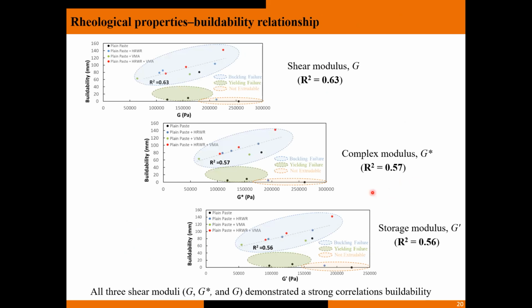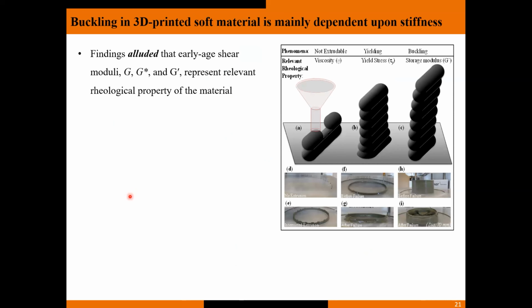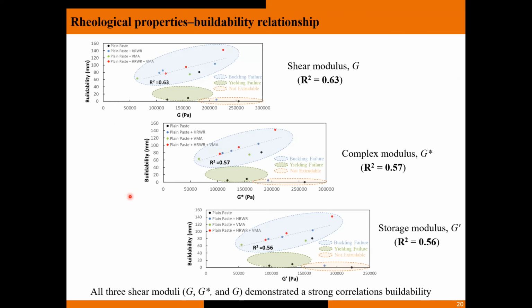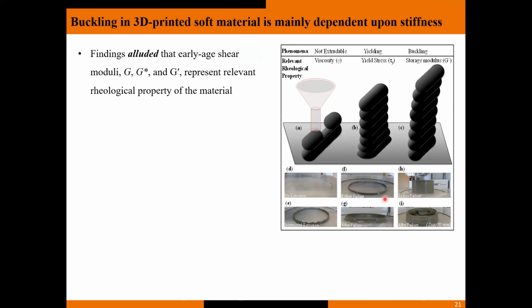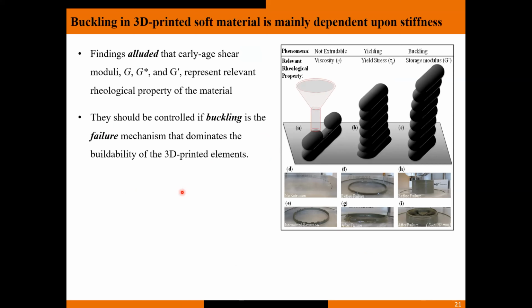So for that, we looked into the correlations of buildability of hollow cylinders with different rheological properties. And what we found was that all three shear moduli associated with elastic properties or stiffness, G, G star, and G prime, demonstrated a stronger correlation with buildability as opposed to yield stress and G double prime. In other words, buckling in 3D printed soft materials is mainly dependent upon stiffness.